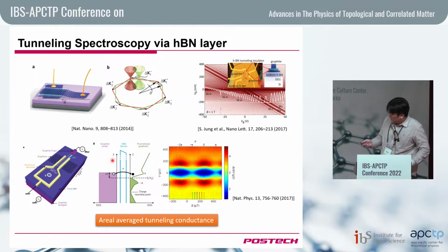For example, from Geim's group, maybe, I'm not sure, but anyway, people have used boron nitride as a tunneling barrier between two graphene layers, and by changing the twisting angle between these two, we can expect different kinds of spectrum. They even show negative differential resistance as well. And people use this technique to see the Landau levels formed in graphene under a strong magnetic field. And Pablo Jarillo-Herrero's group at MIT used this tunneling spectroscopy to see the so-called Andreev bound states inside of the graphene Josephson junction. I will focus on that, so I will explain it in more detail later.